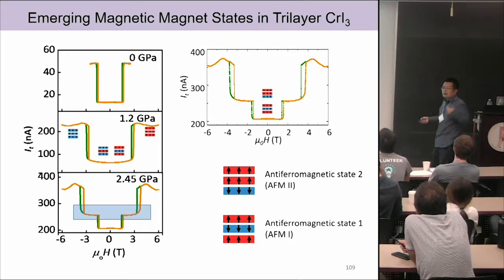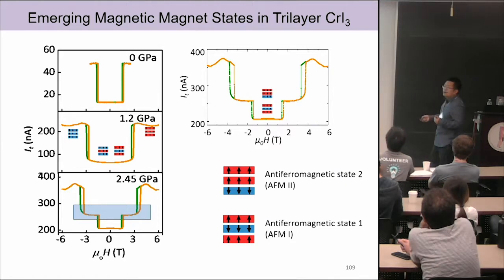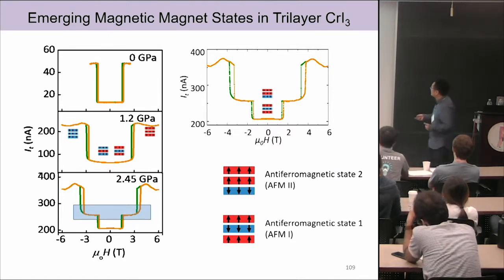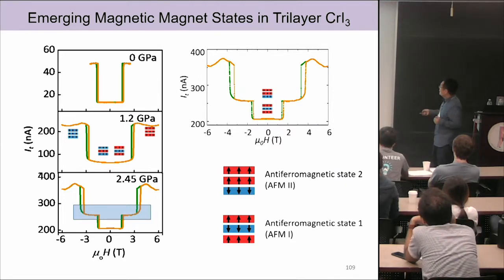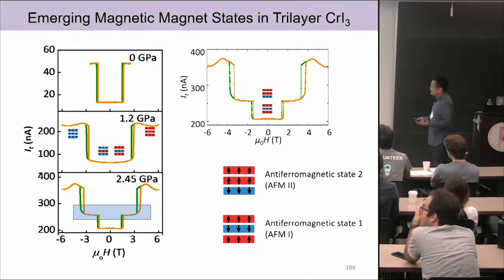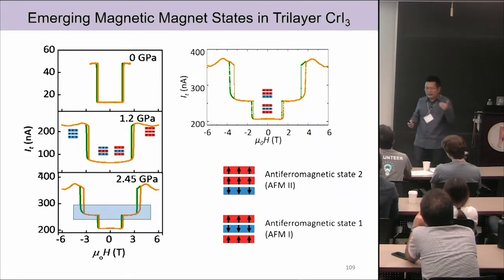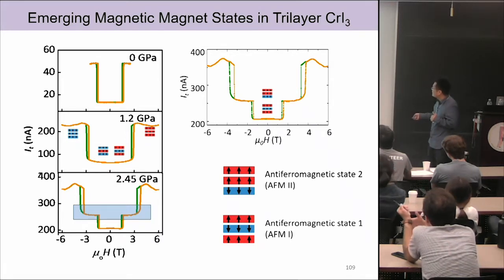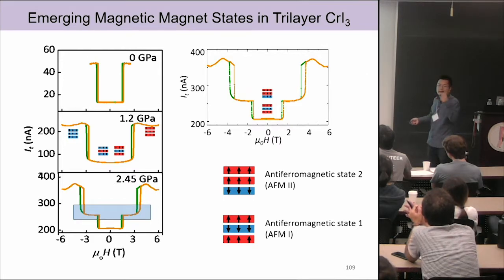So we can confirm this by looking at the spin flip transition. You already know that as we apply the magnetic field, when the Zeeman energy overcomes this interlayer coupling, then the spin will flip. But AF2 only has one interface, and AF1 has two interfaces. So what it means is the energy we need to flip the spins in AF1 has to overcome these two interfaces compared to one interface in AF2. So the critical field we need to flip the spin in AF1 should be twice what we need for AF2. Okay, do you follow this?